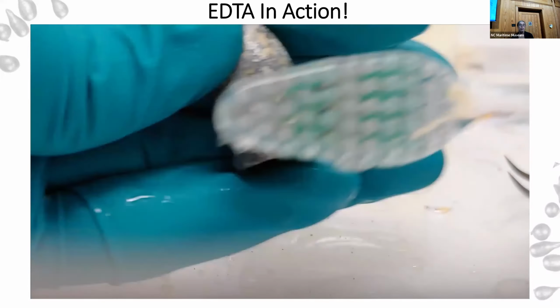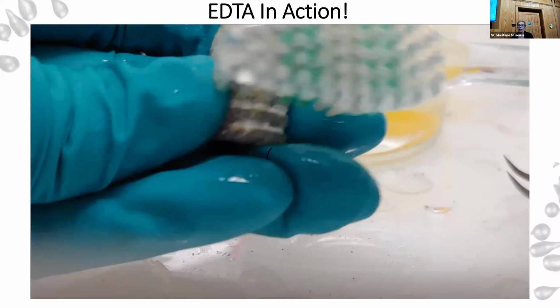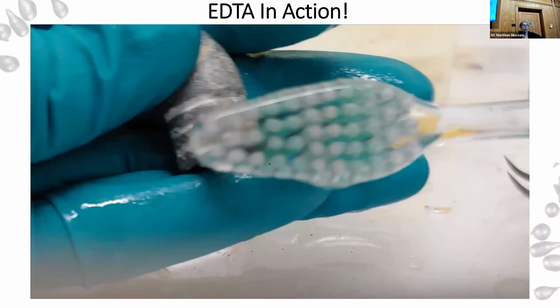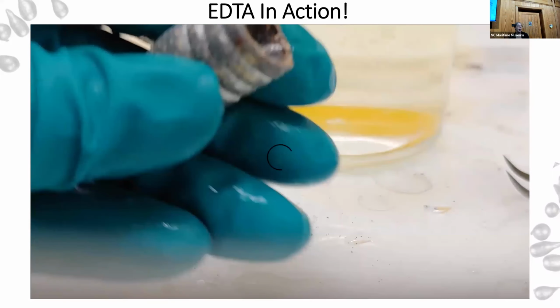So what I'm doing here is essentially, it helps a lot of times as we're buffering. EDTA is pretty good at dissolving a lot of things, but it often doesn't dissolve everything. So to help it along, a lot of times we do use a little bit of mechanical abrasion and cleaning to try to help remove some of that softened up and still partially attached material on the surface to help clean it up some more. So a lot of these treatments, we do use aspects of the things I talked about with these. You often use a lot of different techniques together to try to get the results you want.